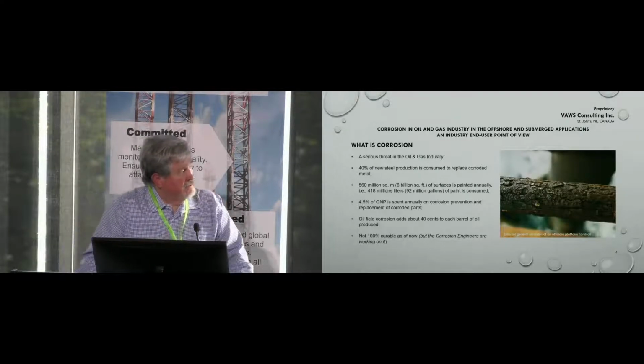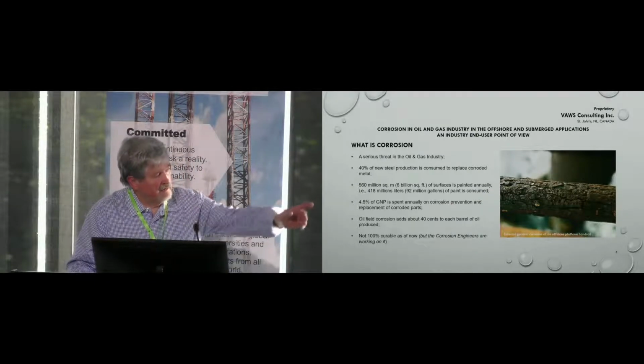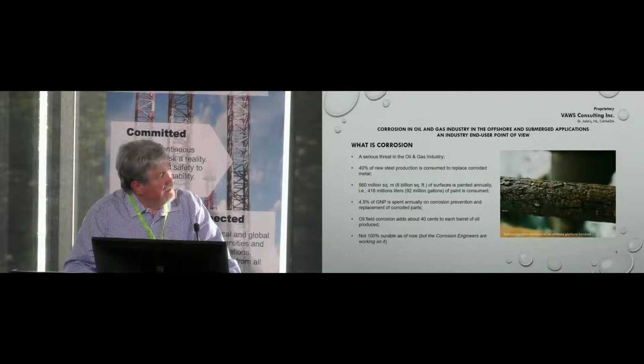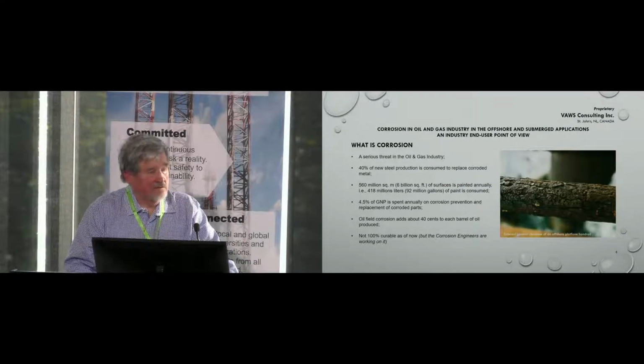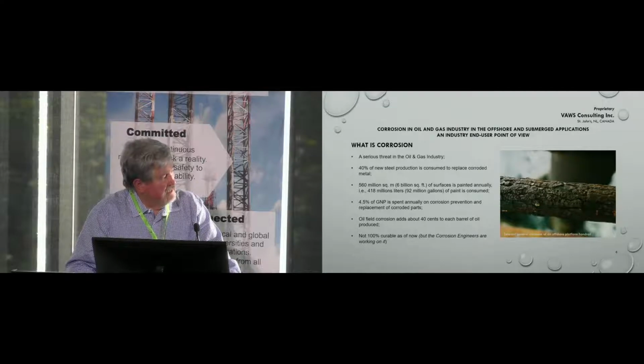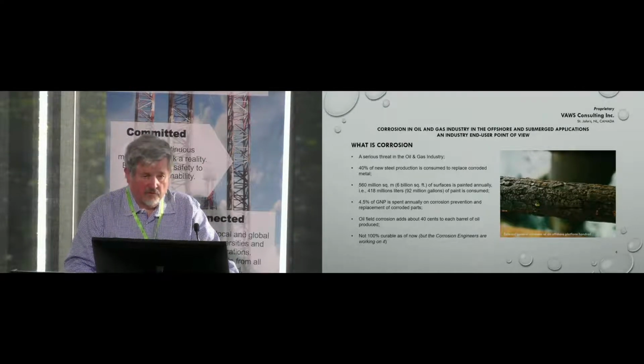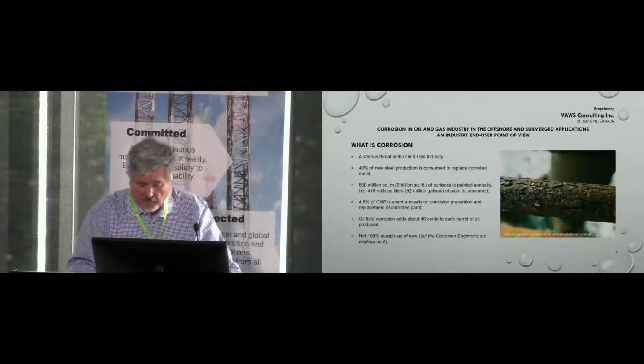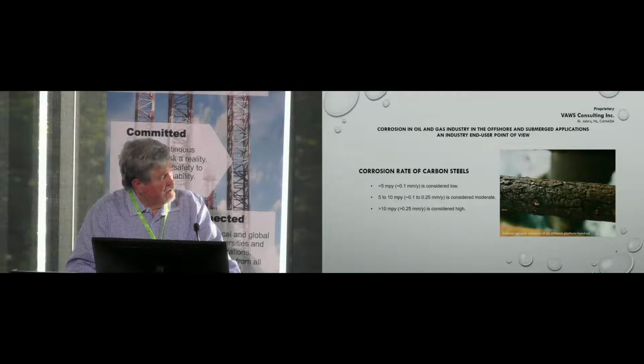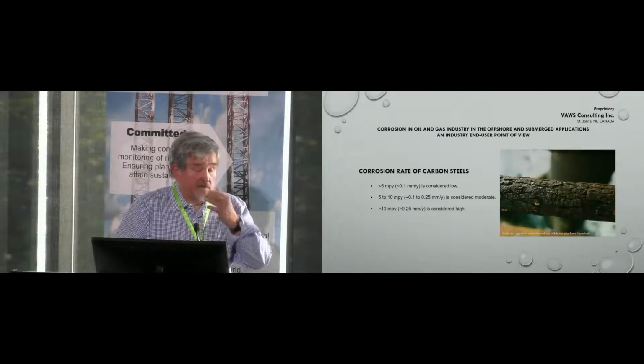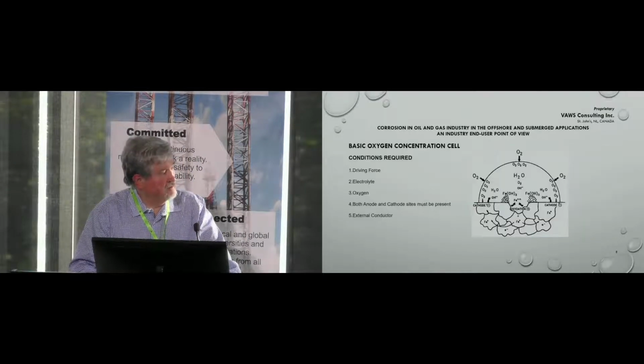Corrosion is a serious threat to the oil and gas industry. By the way, this is a handle on one of the platforms we had. 40% of new steel production is used to replace whatever is corroded, and that represents about 4.5% of GNP around the world. It's a serious concern for people who work in the offshore industry. Typical corrosion rates, as they are categorized, are below 5 MPY, so 0.1 millimeters. High corrosion rates are more than 10 mils per year, or more than 1/4 millimeter per year. That's mostly in the offshore industry, really high corrosion because of chlorides.